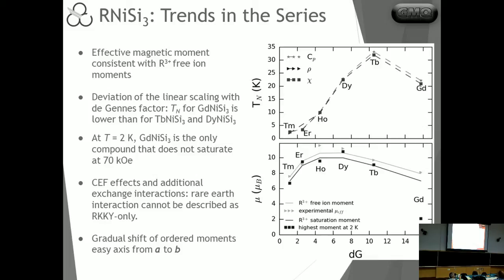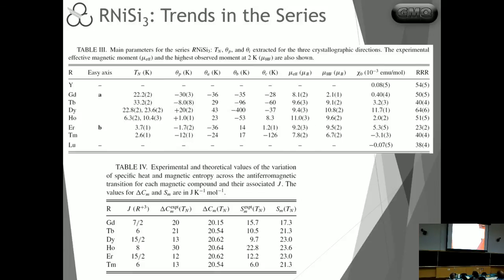In general, when you have these magnetic series, gadolinium is always the highest ordering temperature in any case like this. And as we saw previously, the fact that it does not saturate when we see the metamagnetic transition shows that there's something really strange still going on with gadolinium that we need to work out.